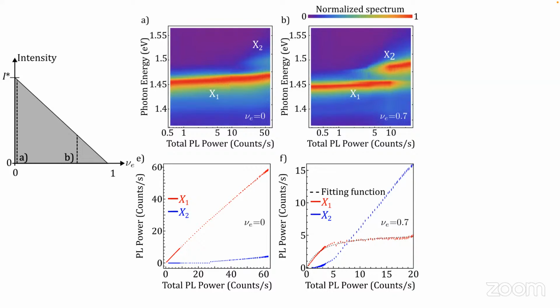So this is a driven dissipative system. We are pumping photons. They strongly interact with each other and they leave the system. And what we see is that they strongly interact, they interact stronger than they decay. Otherwise we would not have been able to see this jump in the PL or in the diffusion. But can we assign a chemical potential or a specific temperature for these driven dissipative systems?